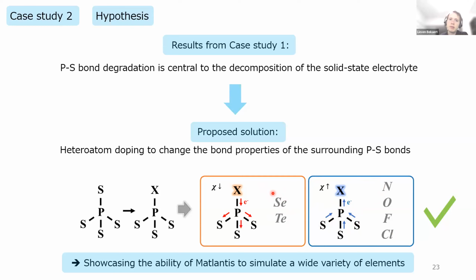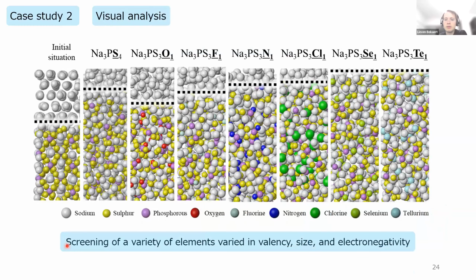So once we confirmed that this hypothesis indeed takes place, we then went on to use Matlantis to simulate these materials. And this really shows another advantage of Matlantis, as I showed you previously, in that you can simulate many different elements using this neural network potential. So here are the output results. We studied many different new materials. Of course, once again, it's difficult to really see what happens, although we can see that for oxygen, a significant amount of sodium remains. So it would lead us to understand that the oxygenated structure has a very good performance.